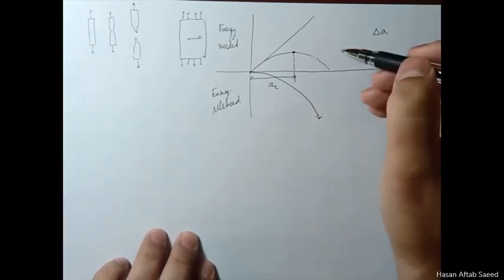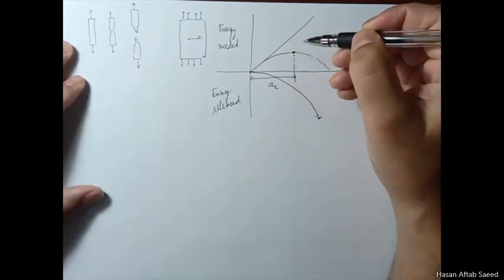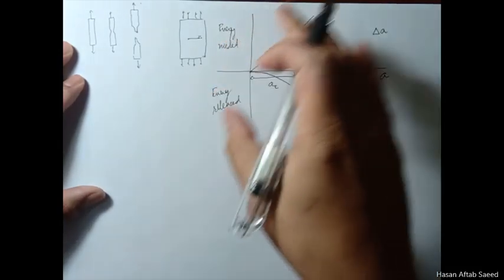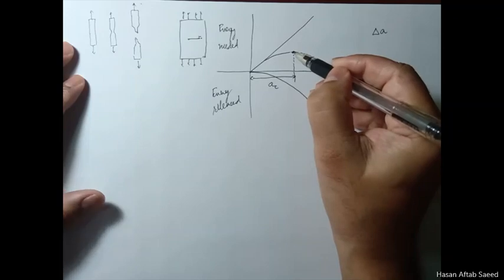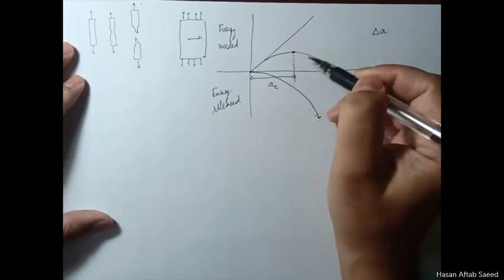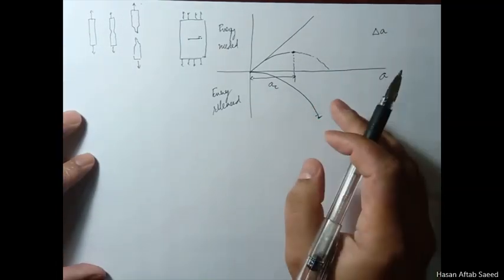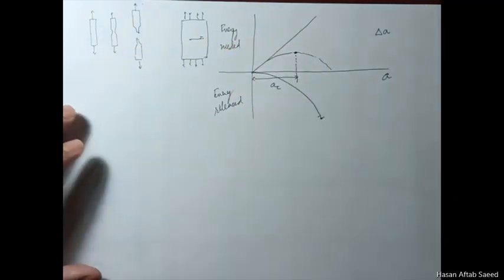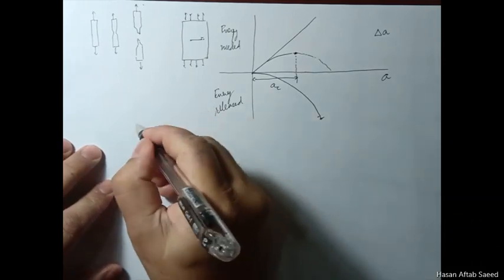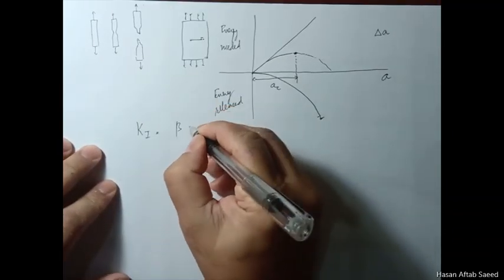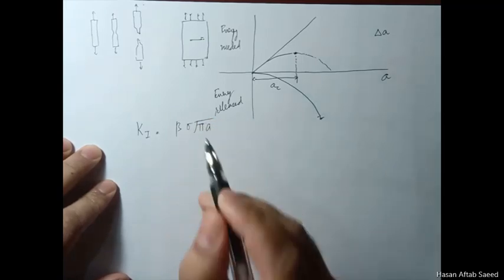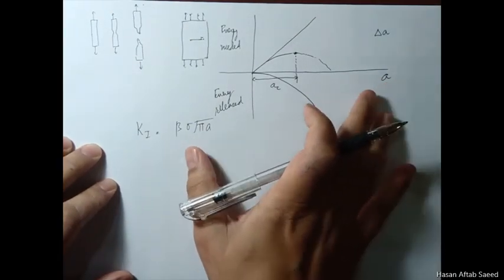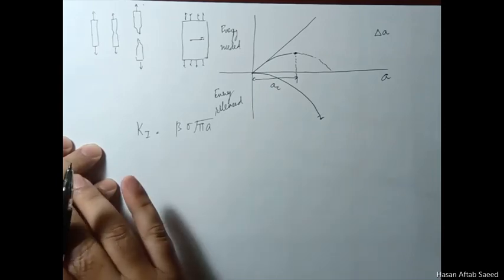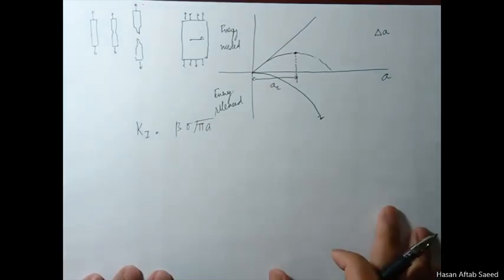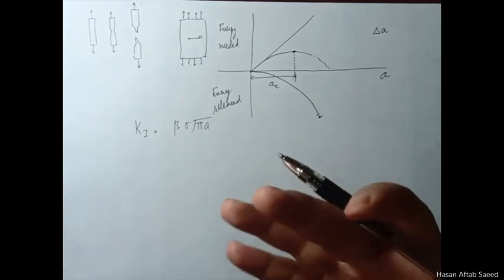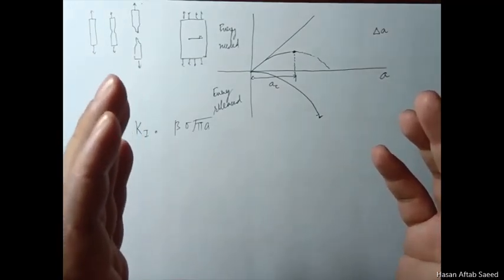So this is what happens when a critical crack length is present in the component somewhere. Then if you apply that stress, that should be enough to extend the crack uncontrollably, because the energy released by the extension will be more than enough to pay for the extension of the crack. So how do we know if a certain K1 value, which we can calculate from this, if we know the crack length and the sigma, is enough for the crack to run away uncontrollably? It's very simple. Just like in the yield case, we compared the stress parameter with the material property, the material property being yield strength.